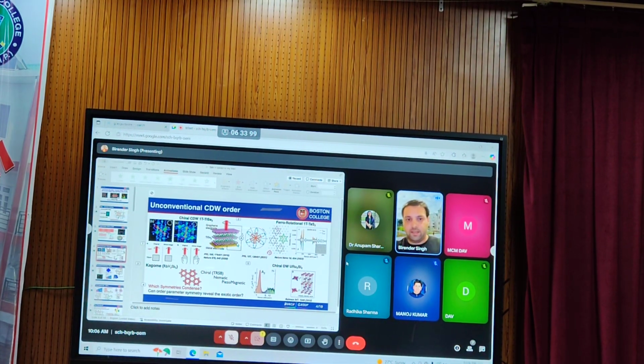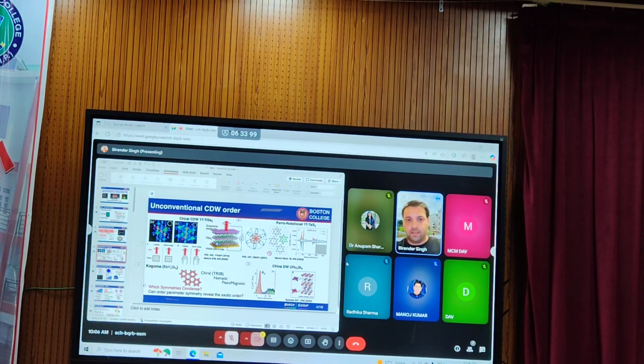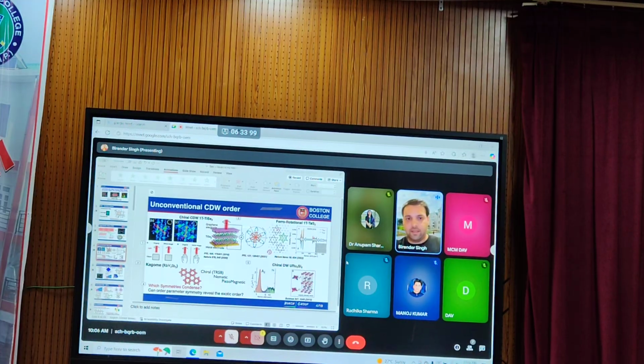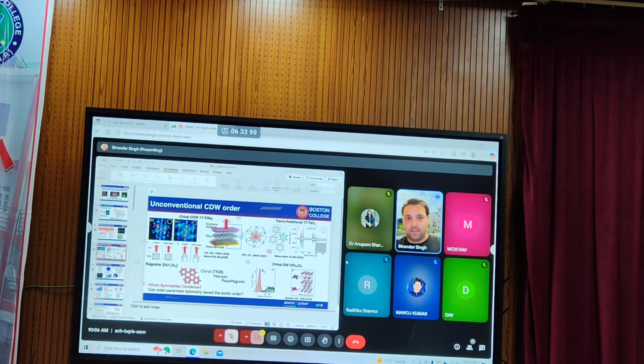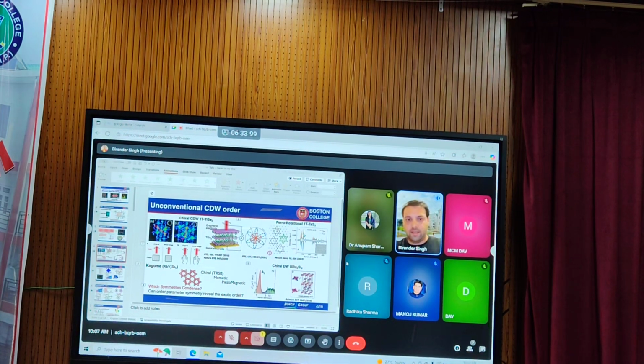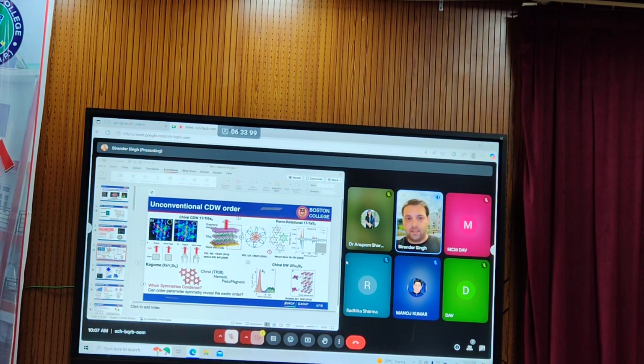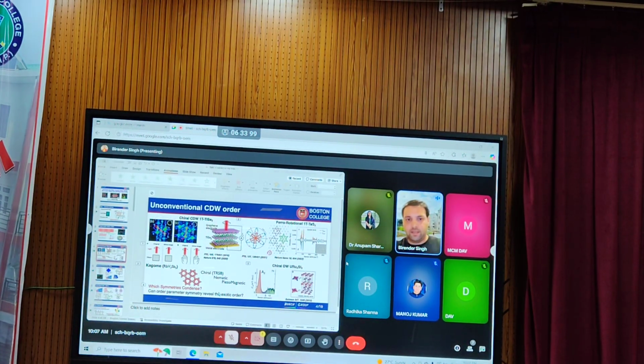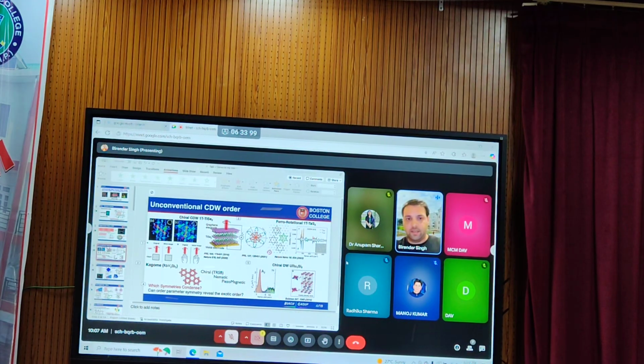So now we thought, let's take a look at the symmetry of these modes. Do they have the same symmetry or different symmetry? First we look at these folded phonon modes. We see they are nicely fourfold in nature, which has Ag and B1g symmetry. This is the intensity plot when we change the polarization of light in parallel and cross fashion. They look quite symmetric and scalar.